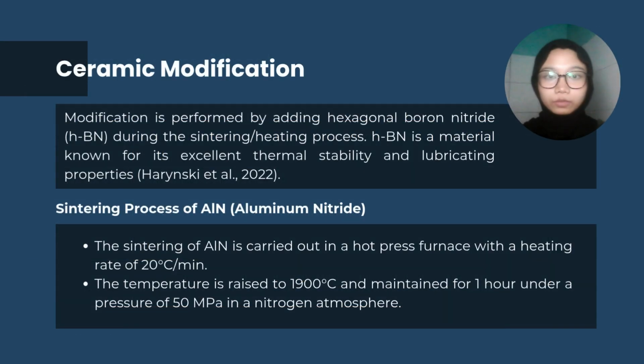Modification of aluminum nitride is performed by adding hexagonal boron nitride, which has excellent thermal stability and lubricating properties, during the sintering or heating process. The sintering of aluminum nitride is carried out in a hot press furnace with a heating rate of 20 degrees Celsius per minute. The temperature is raised to 1900 degrees Celsius and maintained for 1 hour under a pressure of 50 MPa in a nitrogen atmosphere.